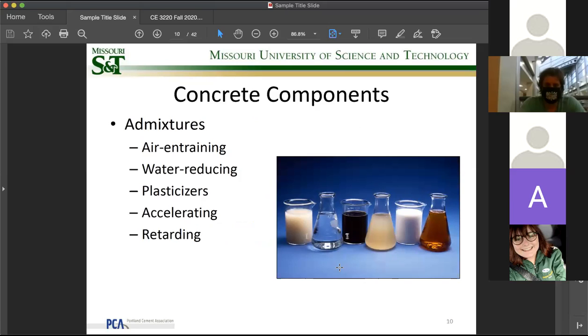So apart from this water cement ratio, the very important factor here is we can have admixtures added to the concrete. We have air entraining, okay? We have water reducing, we have plasticizer, accelerating, retarding. So the invention of these chemical admixtures, the main purpose is to enhance the workability or strength of the concrete. For example, if my concrete has a flow problem, okay, the concrete simply is stuck there, I can add air entrainment, okay? So air entrainment works like tiny lubricants between the aggregates and cement and lets the concrete be more flowable, okay? It's like if you blow bubbles inside muddy water, it actually flows faster, okay?